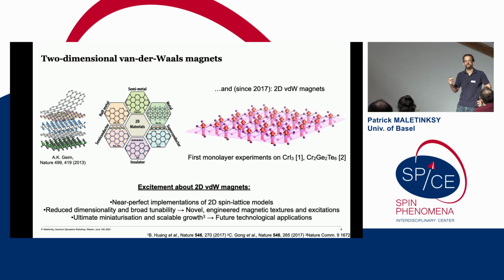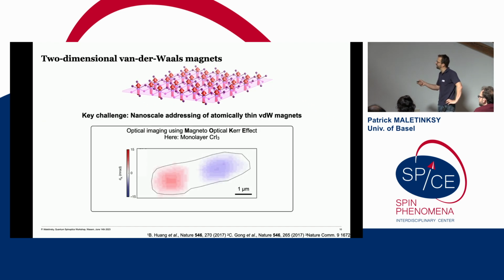Now, there is a challenge, or was a challenge in this field, and that is that it's extremely difficult to address magnetic order in these systems on the nanoscale. And that, of course, has to do with the very weak magnetization at hand that doesn't lend itself to the more traditional imaging and sensing techniques. In fact, in the beginning, when these materials were discovered, pretty much the only tool around for imaging was magneto-optical Kerr effect imaging, an optical technique that has resolution limited by diffraction.